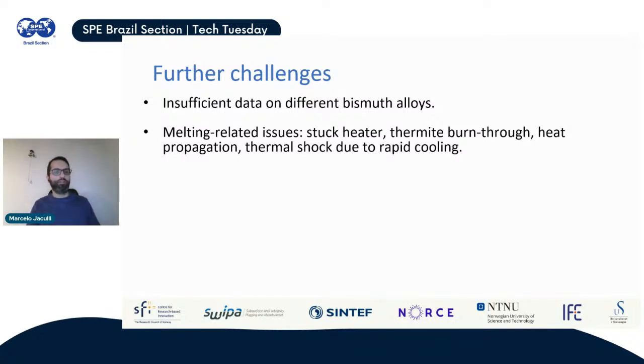You also may have problems with heat propagation. If you're using, for example, thermite, you're generating a lot of heat. This is going to be dissipated into other well barrier elements. So this could be an issue for the casing itself, for the cement that is also behind it, even for the formation perhaps. So it also needs further investigation. You might have some problems with thermal shock if the alloy cools down too fast. This is something that we observed in the lab, and it could be an issue as well when placing the plug downhole. So another heat-related problem.